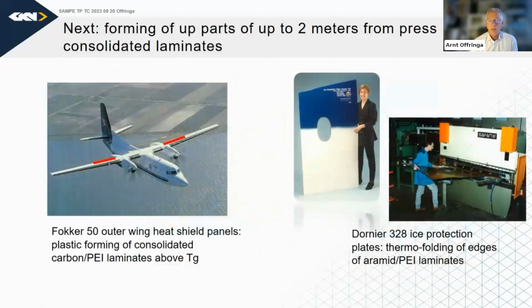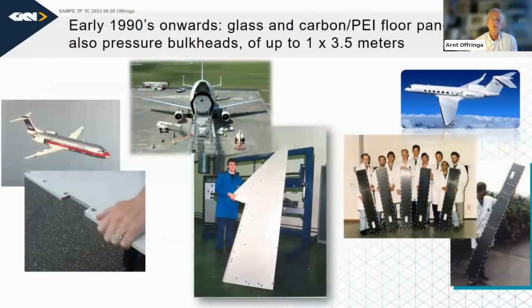Also developing panels for wings with a creep forming process. So not an autoclave process, but creep forming. On the right is a plate which is formed by folding and by ultrasonic welding. So these are all out-of-autoclave processes. So here we are working out of autoclave up to, let's say, about 2 meters dimensions, 3 meters dimensions.